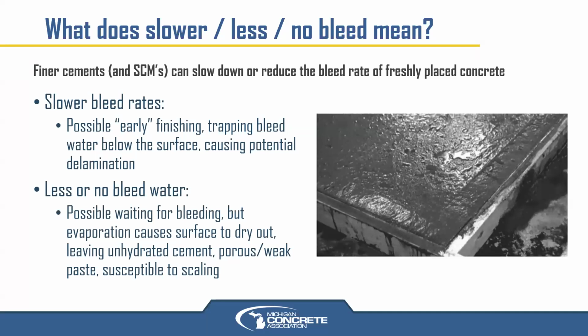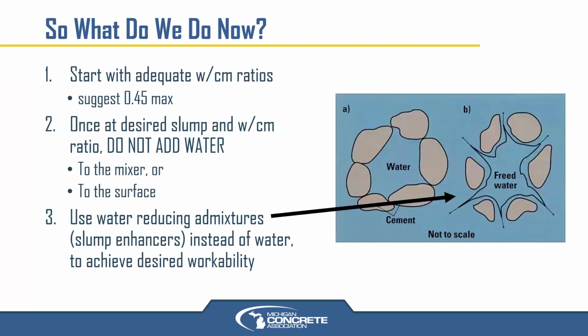It's porous. It hasn't infilled, and it allows things to get in in the future over the winter, perhaps, and cause damage, which then makes it susceptible to scaling. And we'll get into scaling later. But those are things that the bleed water could affect. And those are concerns that you may see on a product. Not always, but just know that this is a change, and so has changed the mixes that we see.